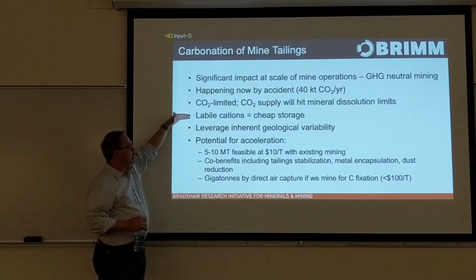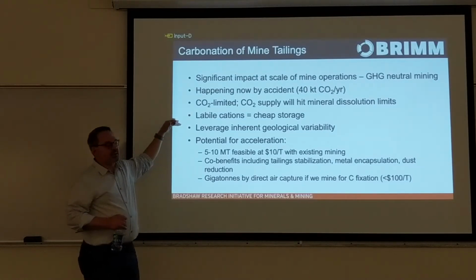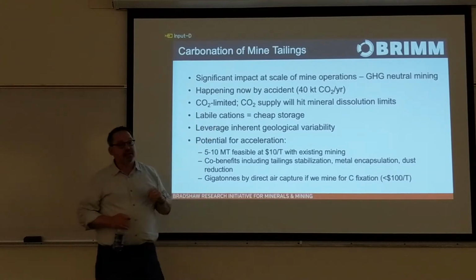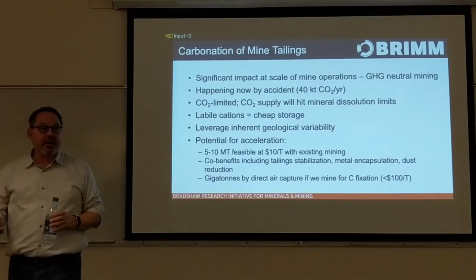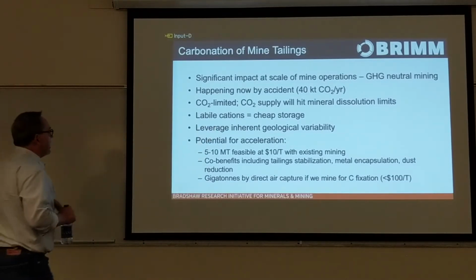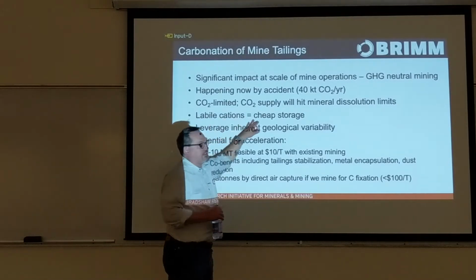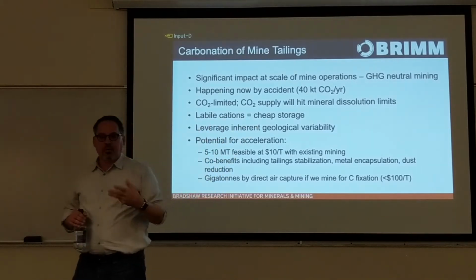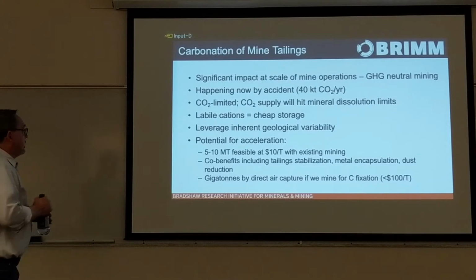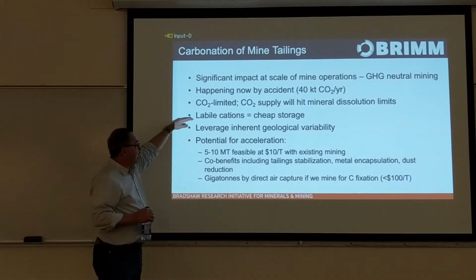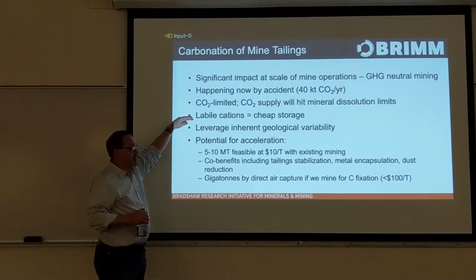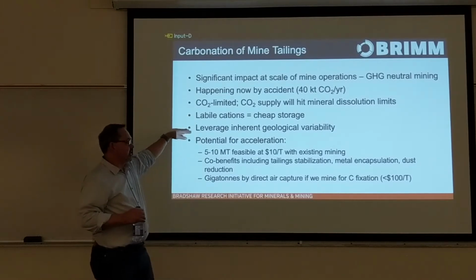So what we do is we characterize tailings both within a deposit and across deposits to find the most reactive material. We call it the labile component, the labile magnesium. And labile magnesium equates to cheap carbon storage because we can pull the cations off quickly. So in essence, we recognize that the deposits within an individual mine are highly variable.